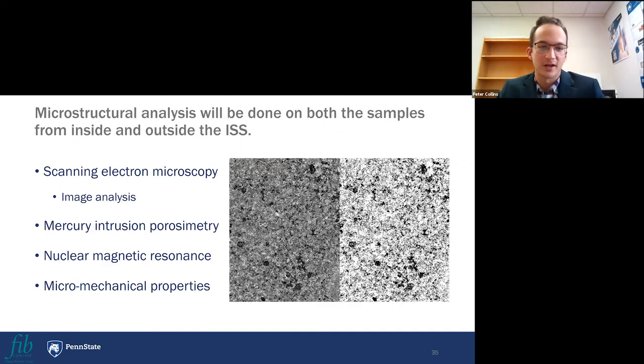So once we get them back, there's a lot of different techniques that we can use. Some of the ones we are planning on right now, of course, is scanning electron microscopy. That is a good way to look at any kind of deformation, cracks, shrinkage effects that may occur, as well as you can combine that and do image analysis. This is something I do pretty frequently with the original MISSE experiment that went to the ISS. We do this all the time, where you can threshold the image and quantify percentages of porosity or the CH or the CSH, as well as the raw materials through that. You can also produce pore size distribution curves and a plethora of things through SEM. It's a very powerful technique.